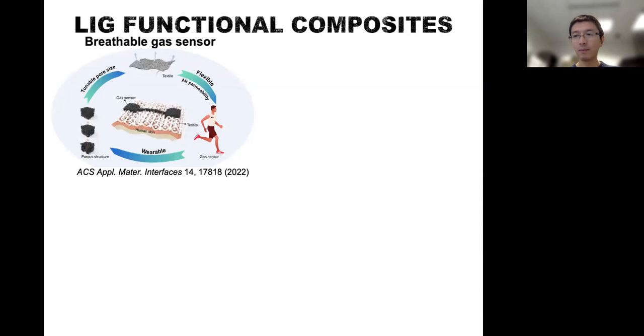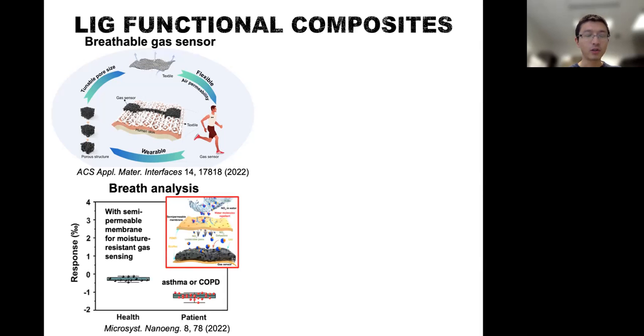And of course, when we are looking at this platform, it does not need to be limited to a particular substrate, even though this is like burning the material into carbon black, and if you tune the laser parameters right, you'll be able to get the porous graphene, but it's still limited to some of the material. So here we explore the so-called block copolymer that can be spin coated onto different substrates. So for example, the textile, different clothing, and you'll be able to create a gas sensor on this porous structure, and that can create a fully breathable gas sensor. And we can also analyze the breaths from the different patient population.